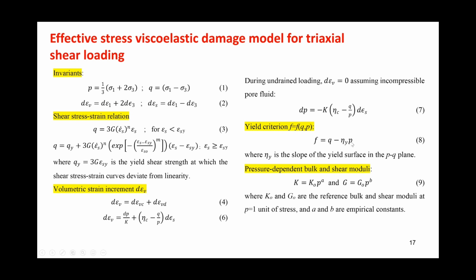Okay, we now have also the yield criterion, because here we only have Q sub Y. So the Q sub Y now is a linear function of the mean stress. So this is just a straight line function, a Mohr-Coulomb function. We also found that the bulk and the shear moduli are dependent on the mean stress according to the power function given here. So the bulk modulus increases as a power function of P, and the shear modulus also increases as a power of P, with exponent B, okay.